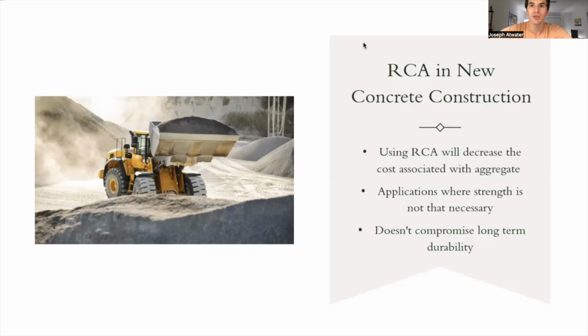Due to RCA having a lower strength than typical aggregates, it will be more useful in areas that don't require high strength specifications. RCA is perfectly suited to be used in lean concrete, curbs and gutters, roadways, and sidewalks. RCA does not increase concrete susceptibility to freeze-thaw cycles despite having a higher permeability. Because of this, it is possible to use RCA in situations where long-term durability is required and not limited to warmer climates.